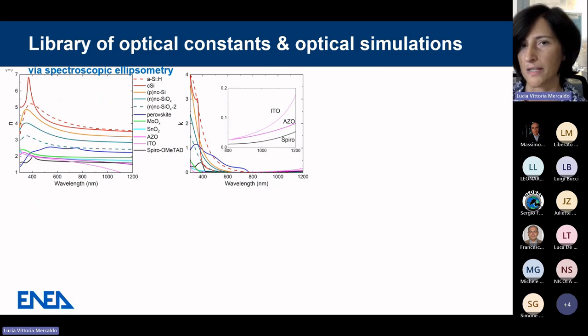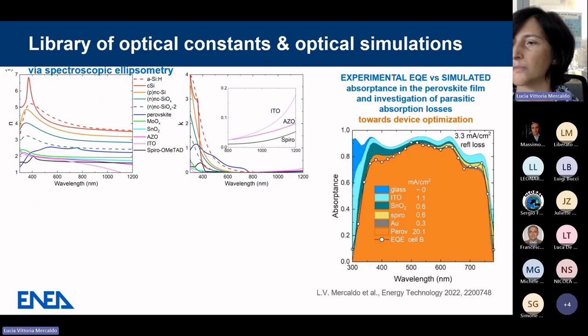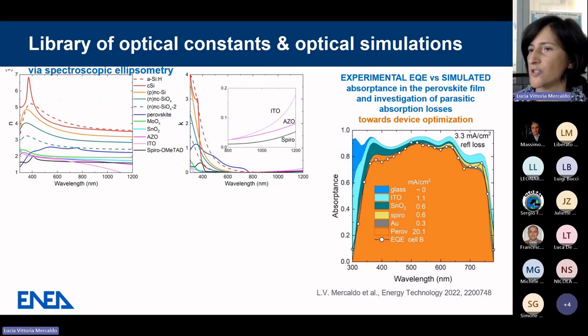And we now have a sort of a library of all the optical constants of all the materials we prepare in our lab, which allows us also to do optical simulations of the solar cells that we make. For example, I'm showing a comparison of the experimental external quantum efficiency of the solar cells prepared in our labs versus the simulation of the absorptance in the perovskite films. And together with this comparison, we actually also could investigate the parasitic absorption losses by the other supportive layers in the structure. And this can be useful toward device optimization.